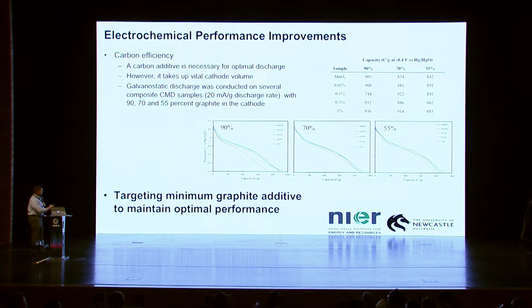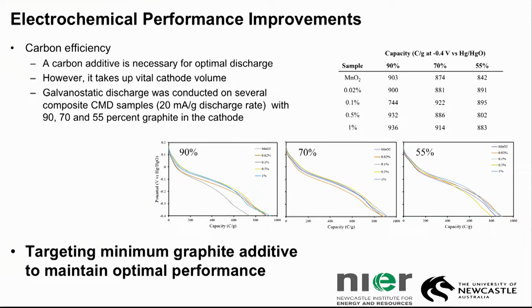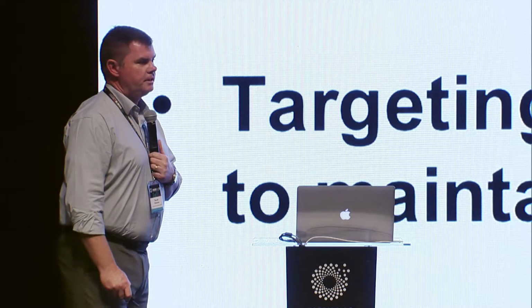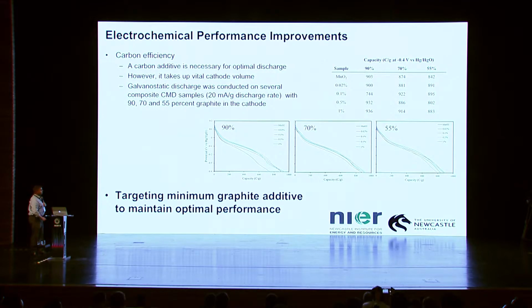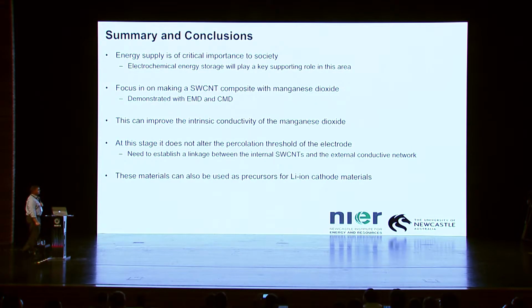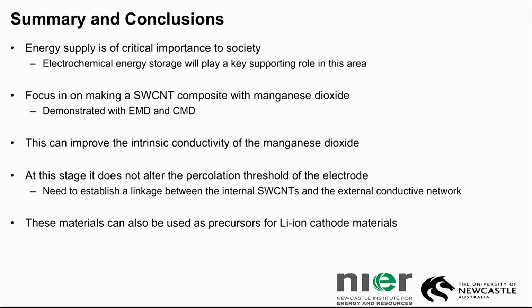Okay. And then these are, again, some information leading to trying to optimize the amount of carbon included into the material. And really what we're doing here is focusing on carbon efficiency, basically examining the optimum amount of carbon that's necessary for conductivity and for performance, all the while minimizing the amount of inactive conductor within the system. All right. So with that, there's just a couple of key outcomes from our work, mainly associated with the conductivity of these materials and their performance.